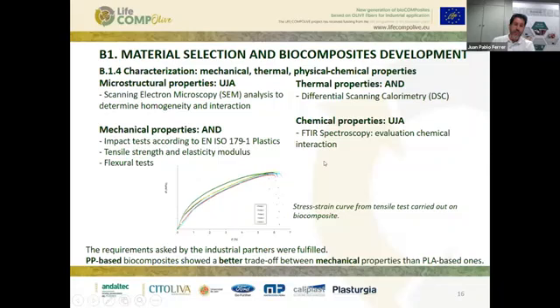And then we characterize those composites obtained in the laboratory. We perform the microstructural characterization, the thermal characterization, also the chemical characterization, and the mechanical characterization. We can see an example of the stress-strain curve from a tensile test carried out on that biocomposite.